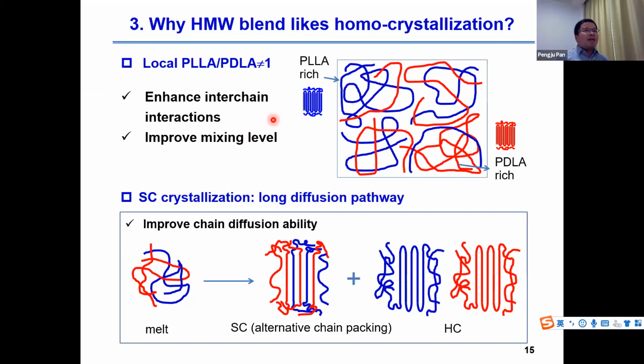Because the mixing level can be improved by increasing the interchain interaction between the L and D polymer, we believe enhancing the interchain interaction can improve the stereocomplex crystallization. On the other hand, compared to the conventional homocrystallization, stereocomplex crystallization needs an alternative packing of PLA and PDLA. It has a long diffusion pathway and is more controlled by the chain diffusion in polymer crystallization. So we believe enhancing the diffusion ability of polymer chain can also improve the stereocomplex crystallization.